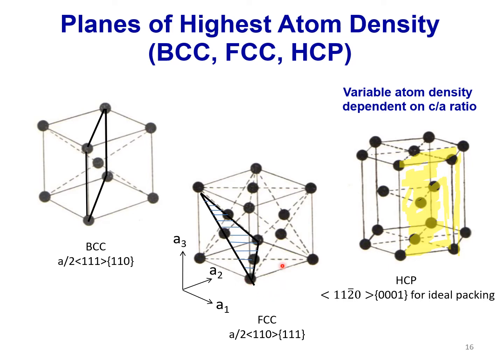Face-centered cubic structure. Here's the atoms at the face centers, and because of that, the close packed plane, the one in which we stack up the little table tennis balls, is the 1-1-1 plane. So this plane and then this plane correspond, and then this plane, so that would be A, B, C stacking, is how one would look at the position of the atoms in an FCC structure.